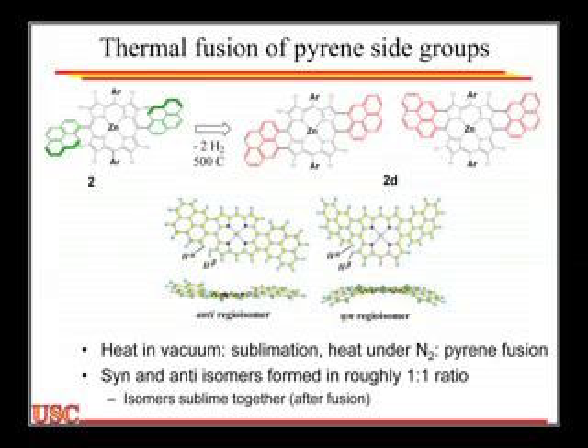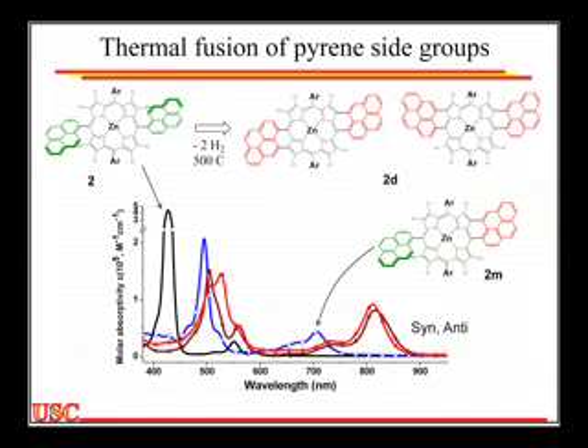What if I treat that with iron using what's called Scholl conditions? I can fuse that and make this doubly fused pyrene compound. And so now we get a marked redshift and an increase in intensity by quite a lot. So the intensity goes up by about 30%. I get a redshift out beyond 1200 nanometers. The tail is out to 14. We've actually, using this same system, gotten to absorption out to about 1800 nanometers.